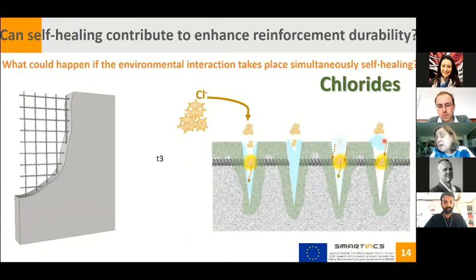Or we can have a sealing from the surface, but this could be not enough to avoid the penetration of the aggressive agents, and finally the corrosion to be initiated. However, it could be a very challenging aspect, and the most interesting one, that the self-healing of the crack is dense enough to avoid the penetration of the aggressive agents, and the kinetics will be fast enough to allow the self-healing of the crack before the aggressive agents penetrate to the rebar and initiate corrosion.